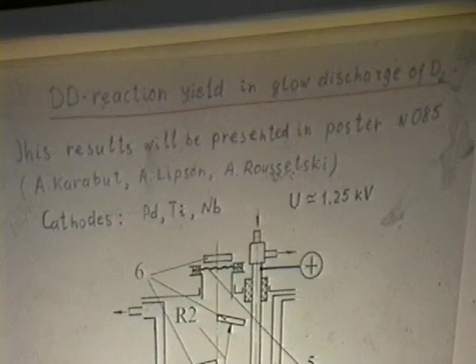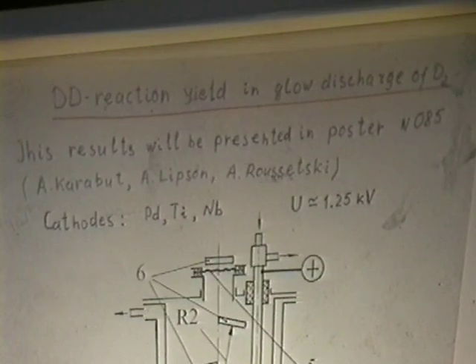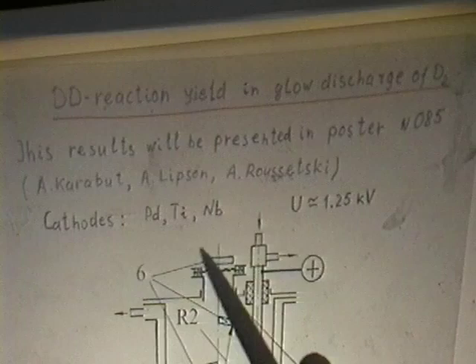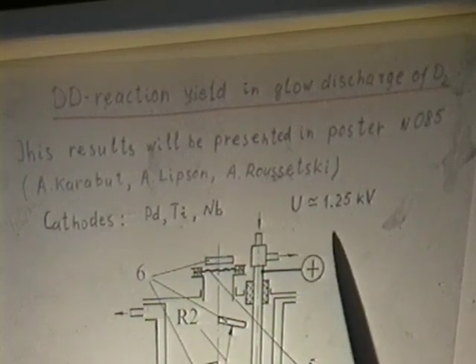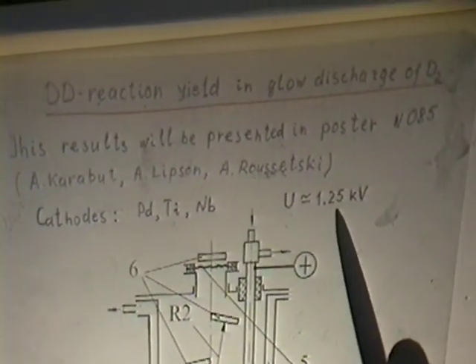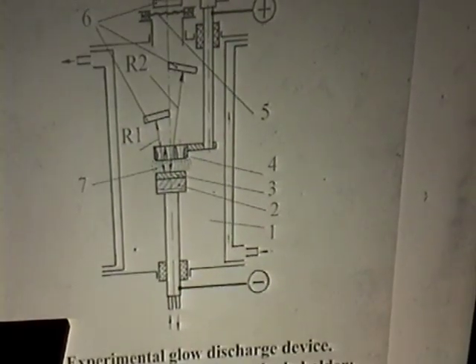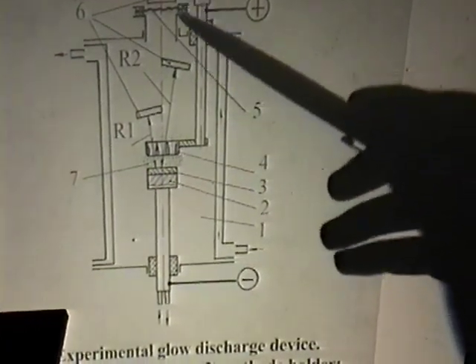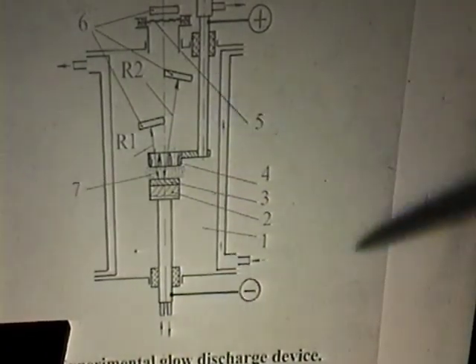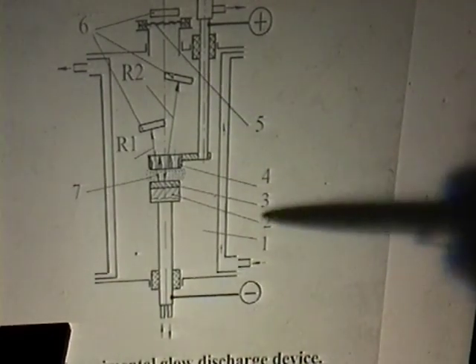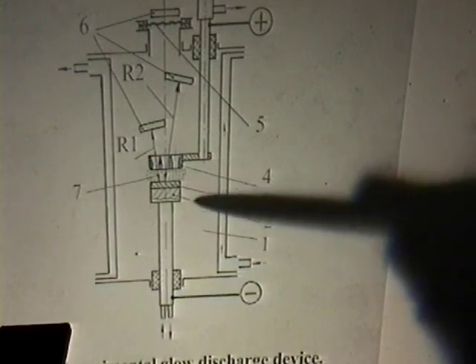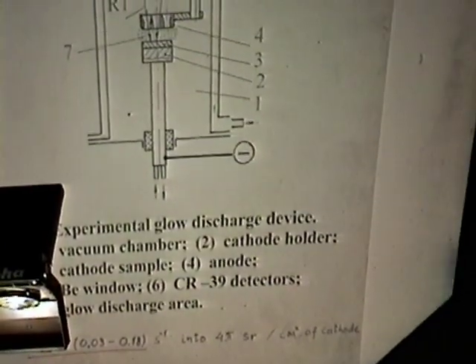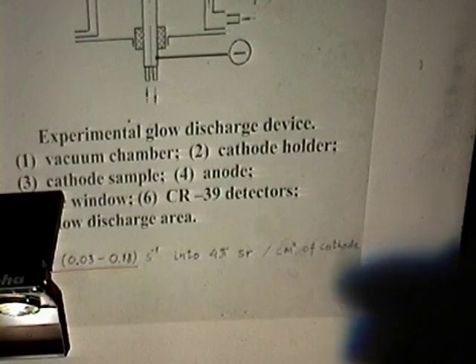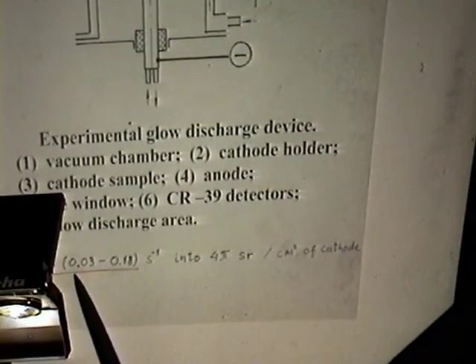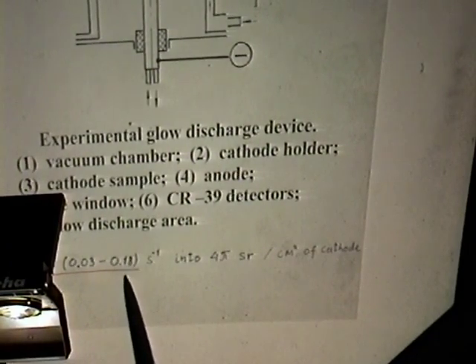Tomorrow. Briefly, I can say that we used different cathodes like palladium, titanium, niobium at the voltage of glow discharge near 1.25 kilovolts. The track detectors were placed at different distances and protected by different absorbers to prevent ultraviolet irradiation of detectors from the glow discharge area. We estimate the deuterium yield in this experiment as a value from 0.03 to 0.18 per second into 4π per square centimeter of cathode.